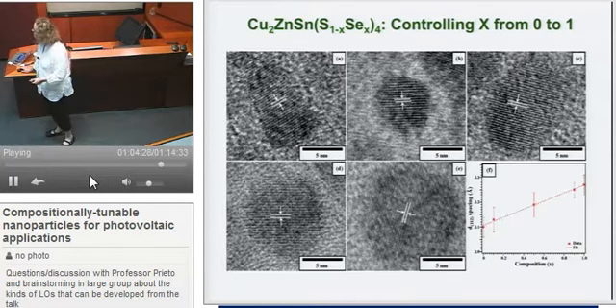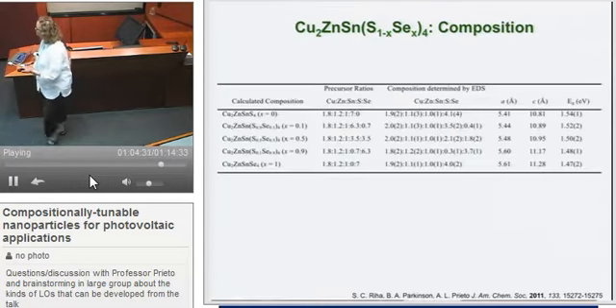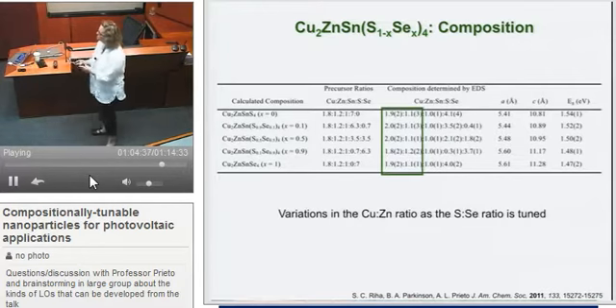So the error bars are pretty big, but at least it shows that the trend goes in the direction that we would expect. Now, this is a lot of data, but this is where I highlight the lack of control in a way. The first thing we noticed, if we look at the copper to zinc ratio, is that we sort of lost our ability to control that in terms of making all the particles copper deficient and zinc rich.